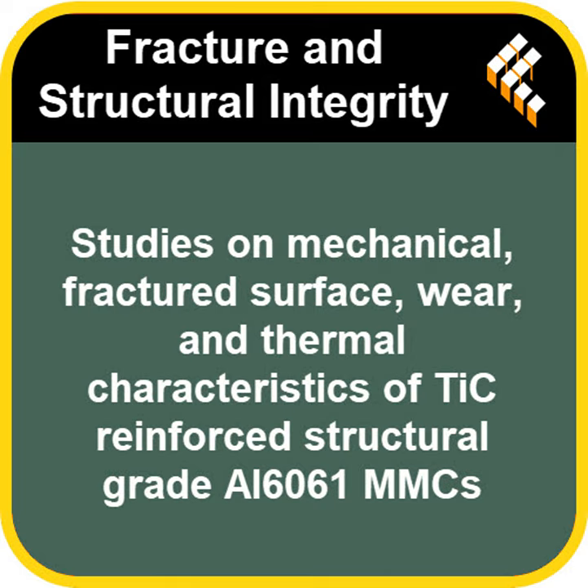However, the TiC-reinforced composites showed something different. Small, flat, cleavage facets on their fracture surfaces. Cleavage facet sounds sharper, more brittle. Exactly. It indicates a shift towards a more brittle fracture mode, less stretching, more snapping. This is driven by the presence of those stiff TiC particles, and also the inherent differences in thermal expansion between the ceramic and the aluminum matrix. Creates internal stresses. And interestingly, the amount of these brittle cleavage characteristics actually increased with higher TiC reinforcement, further emphasizing that delicate balance we talked about.